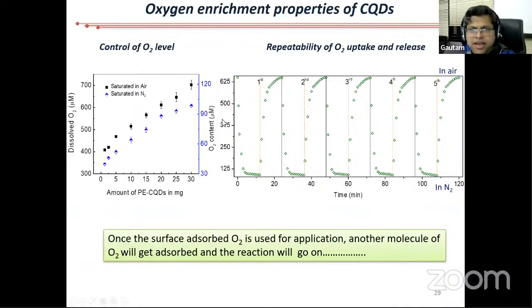So again, here you can see when you pass air into it, it goes down. Then you just leave it, it again takes oxygen from air. It goes down, it again takes oxygen from air. So if you pass some gas, it will release oxygen and it will take it back. This is simple. The same thing will happen if you take any material, but the amount of oxygen that it can take and release is extremely high.